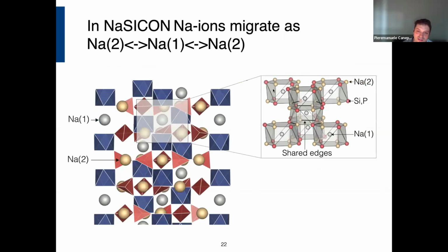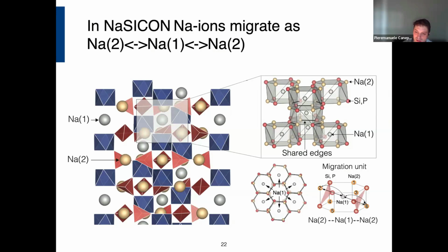Again, let's look again at the structure of this NASICON. I will show this structure from a slightly different perspective. I told you there are two types of sodium, and now the attention should be on the sodium. There are the sodium 2 type of sites, these gold ions, and the silver balls are the sodium 1 sites. What I indicate here as red balls are either silicate, meaning SiO4, or PO4 units. So I can simplify the picture and look at this pseudo-hexagonal prism unit, where six of the corners are sodium 2 ions, and the central ion indicated in gray is the sodium 1 ion.